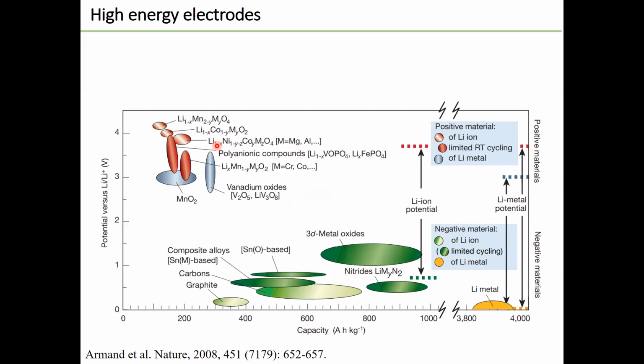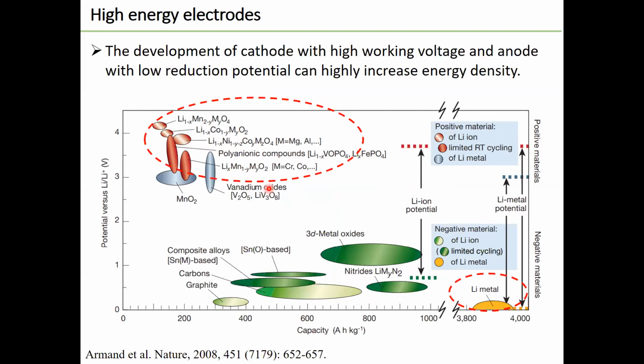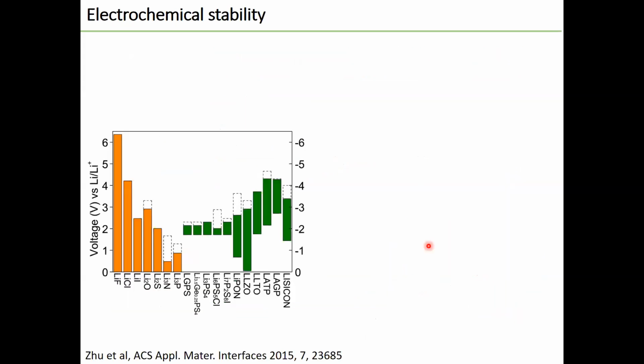As to the energy density, electrodes, including cathode and anode, play the most important role. Based on the calculation, the development of cathode with high working voltage and anode with low reduction potential can highly increase energy density. For the cathode, such as this layered transition metal oxide, it can work at high voltage higher than 4 volts. Lithium metal is the ideal anode for lithium batteries due to its ultra-high capacity and lowest reduction potential. It is a great chance to match this cathode and anode with sulfide electrolyte to achieve high energy density and highly safe batteries.